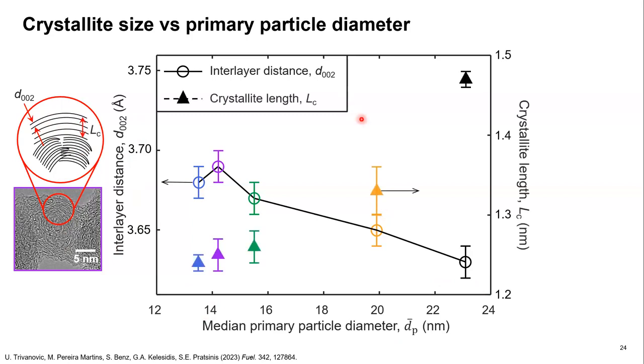The next thing that we can get from XRD is the crystallite length. So we have these different discrete layers that are crystalline, and we get the average length of those layers, of these regions, from the XRD. And this shows even more convincingly that we have this correlation between the size of these crystallite regions and the median primary particle diameter. So it increases significantly for these largest primary particles. And I will highlight again that XRD requires slightly larger amounts of soot in a powder form. By having these high concentrations, we are really enabled to extract this data potentially for the first time, because this is something that's not often measured in aerosol diagnostics because it's harder to collect these larger quantities.